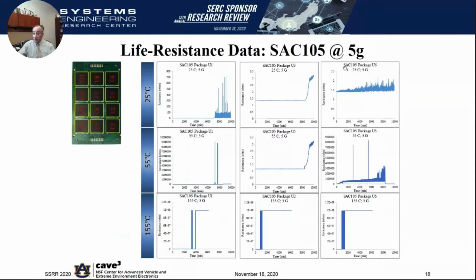So that's takeaway number one. Secondly, if I was to compare these graphs amongst each other, the time to failure varies as a function of location, which is unique to vibration. Generally speaking, in a thermal exposure, you would not have that because that's a more isothermal form of stress, but in vibration and, more importantly, overlapping temperature vibration, you would expect that much more frequently. So that's the second thing that you would see as well.